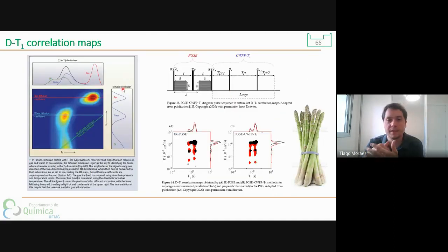Also, we have different pulse sequences for two-dimensional analysis. Like in this situation, we can analyze the diffusion of the molecules as a function of the relaxation times. For example, in this picture, you see that in one-dimensional relaxation times, the water, the oil, and the gas are almost all together here, but they have different diffusion coefficients, right? Of the gas, the water here, and the oil here.